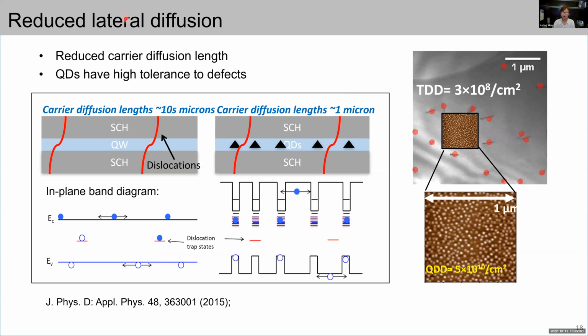And the second part we are talking about is the carrier diffusion length. The typical value of carrier diffusion length for quantum wells is around 10 microns, but for quantum dots it is 10 times smaller. So in the case of a relatively high threading dislocation density, highlighted as these red lines, carriers in the quantum wells are free to move around in the plane of the well, and they can encounter a defect before they recombine radiatively. In a quantum dot, however, due to the reduced carrier diffusion length and the reduced carrier migration to dislocations, the chance to be trapped by the dislocation trap state is greatly reduced.